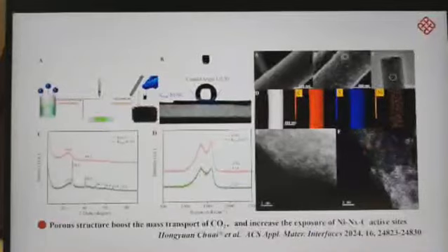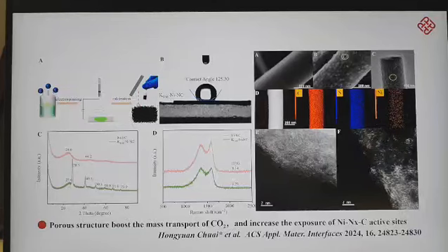Then, we used potassium chloride as a pore-forming agent, PVP as a carbon and nitrogen source, and nickel nitrate as a nickel source to prepare a self-supported carbon-based electrode with mesoporous structure. Compared to the high molecular weight PMMA, which melts to form open-ended tubular through pores, the melting of the small molecule inorganic pore-forming agent, potassium chloride, resulted in more abundant dot-like pores on the surface of the carbon fibers.